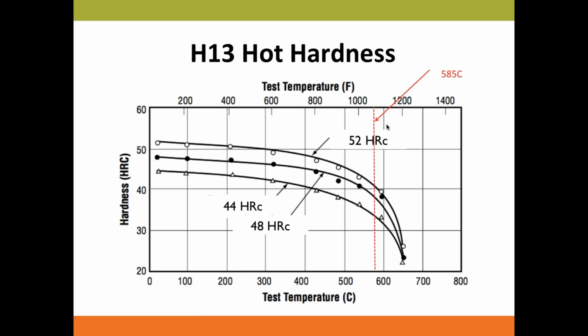And in the second graph, you see, let's say we start with 44 Rockwell compared to the other H13 at 48 Rockwell at cold, which is the room temperature, and then you put these two steels at different temperatures from 100, 200 up to almost 650. We can see the trend of how the Rockwell drops. And what's interesting is if you start with 4 Rockwell difference, they will end up with 4 Rockwell difference up to roughly 585 degrees Celsius.